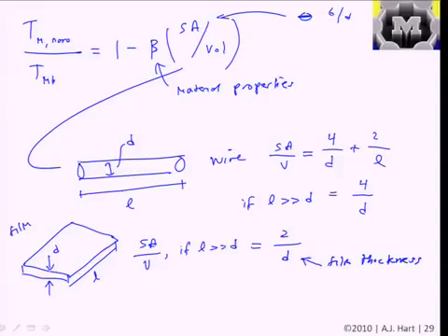So by this kind of dimensionality, you can see that the amount of suppression of the melting point will be relatively less if we increase the dimensionality of our system. In this ratio of 6 over d, 4 over d, 2 over d, the melting point suppression of a sphere versus a wire versus a plate would be correspondingly less, and a plate would melt at a temperature that's closer to the bulk melting point than, say, a nanoparticle of the same diameter as the film thickness.